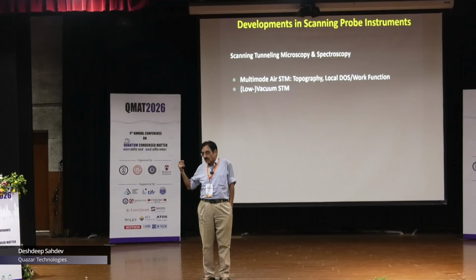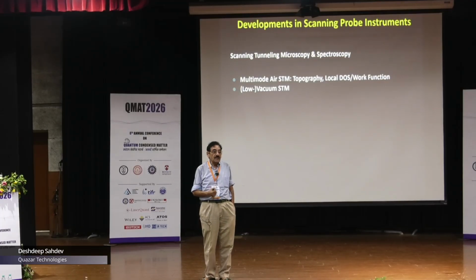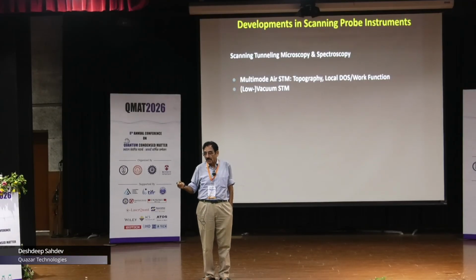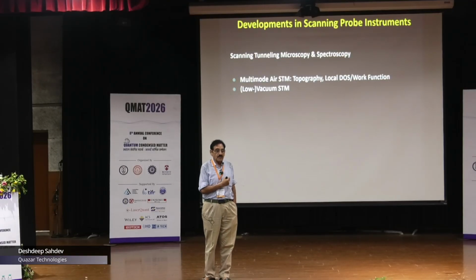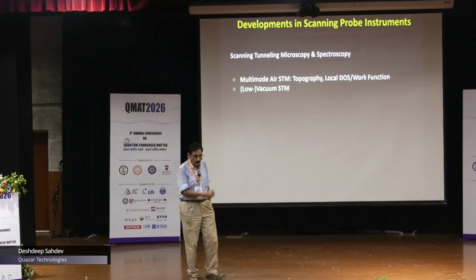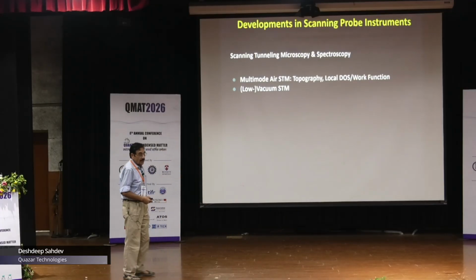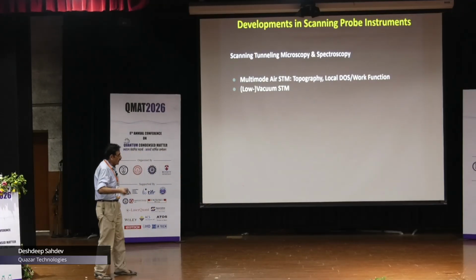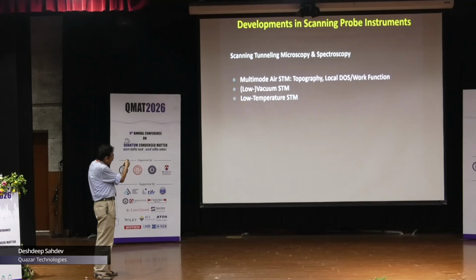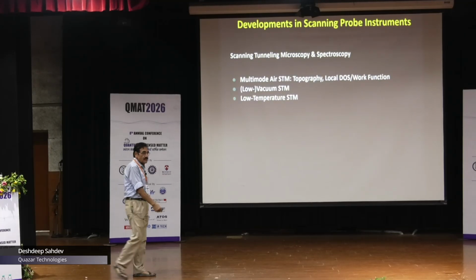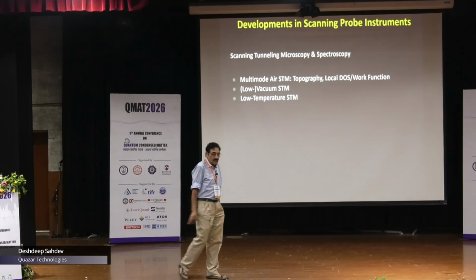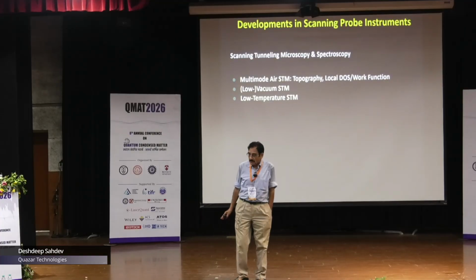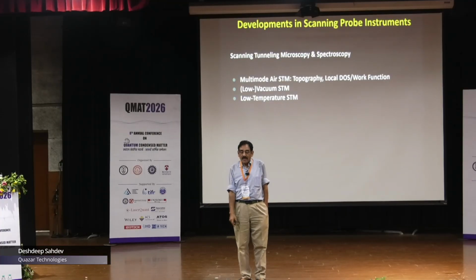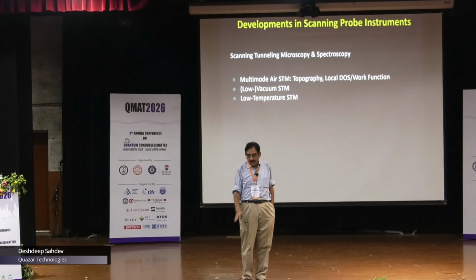So what you do is that you pump with a rotary, and then you connect it to a sorption pump, which has absolutely no vibrations, and you can hold that vacuum for about 5 hours without a problem. And then you'd have to recharge and go through the cycle again. And then we've taken it down to liquid nitrogen temperatures. Liquid nitrogen is easy to work with. It's also very inexpensive and generally available. And it's the same price as full cream milk.